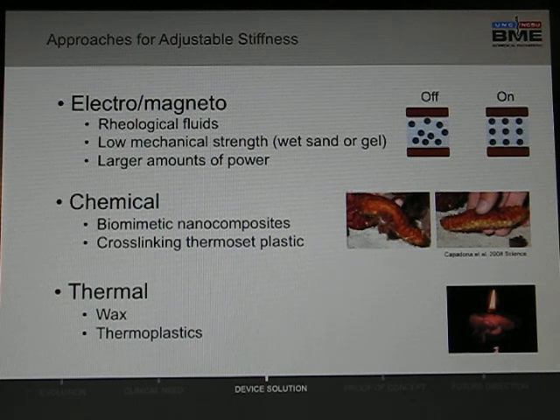Here are a few approaches listed to adjust stiffness. Electromagnetorheological fluids have particles which, when large amounts of power are applied, can align, resulting in the fluid's apparent viscosity changing. It can go from a consistency of something like water to that of wet sand or gel. You can also chemically induce stiffness change by forming and breaking of hydrogen bonds. Biomimetic nanocomposites are a good example, and it's inspired from sea cucumbers. They are able to chemically change stiffness.